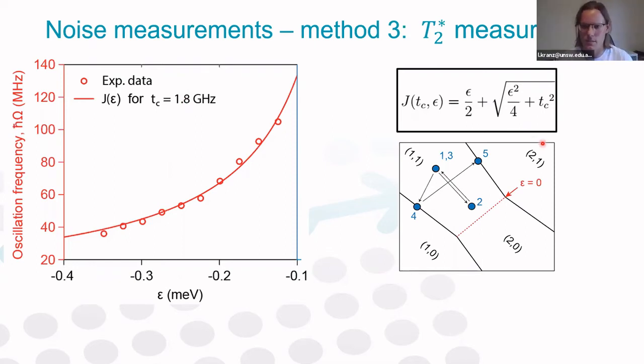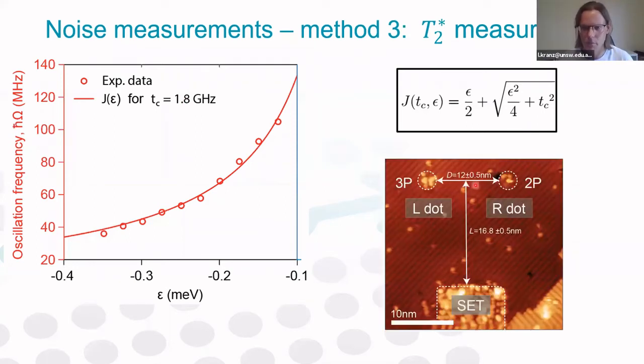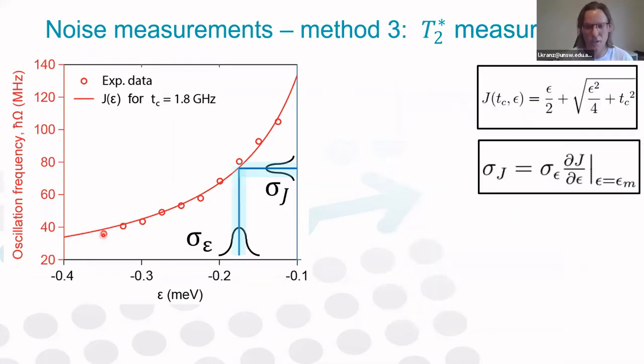And in our devices, the tunnel coupling parameter is linked to this inter-qubit distance, which in this case is 12 nanometers. And we actually noticed that tunnel coupling is very sensitive to this distance. And so this device has been engineered on atomic scale to get this appreciable tunability of exchange interaction with gate voltages. Okay, so now I'm going to try and give you a more intuitive understanding as to why we have decay in our exchange oscillations.